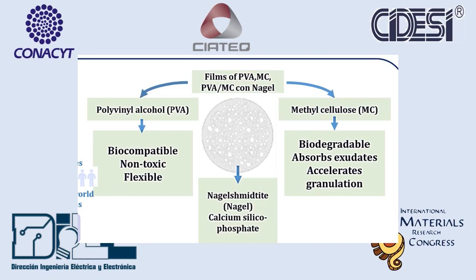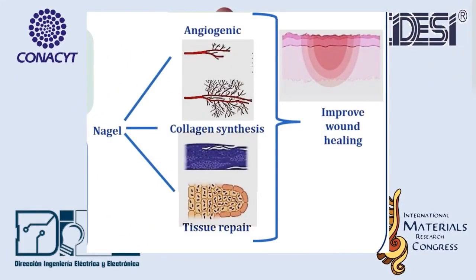For this work, we developed composite dressings from biopolymers such as methyl cellulose and polyvinyl alcohol. These biopolymers have properties such as biocompatibility, absorbability, degradability, and good mechanical properties. They make them ideal for developing dressings. The formulation of the composite dressing was developed by adding NAGEL particles to the polymer matrix, which are calcium silicophosphate that has been shown to stimulate mechanisms that can improve the wound regeneration process such as angiogenesis, collagen synthesis, and cell proliferation.